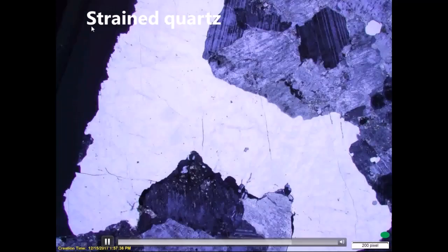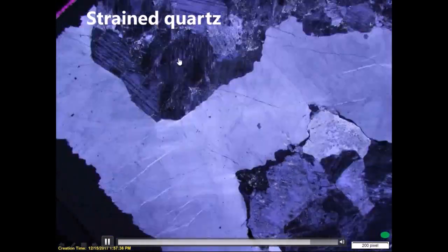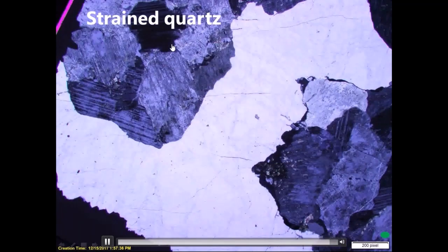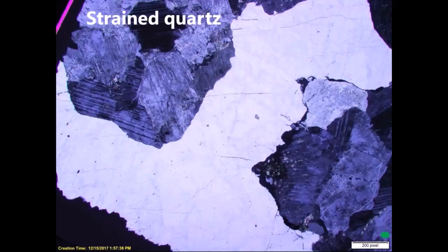In other words, it's strained because Mother Nature applied enough heat and pressure to that quartz to actually bend the atomic structure of that quartz, making it optically do that. But in the course of bending the atomic lattice, Mother Nature has made that particular grain of quartz really susceptible to alkali and water interaction, therefore forming ASR. So identifying strained quartz is a lot of what I do.